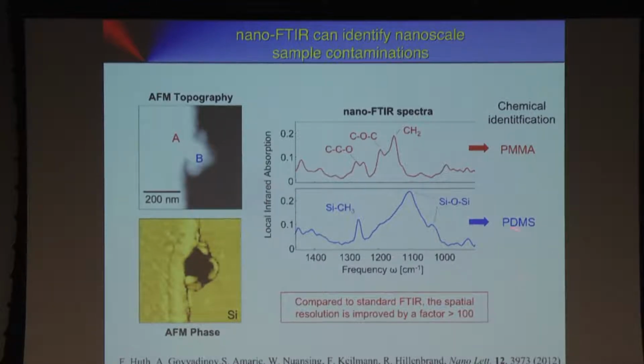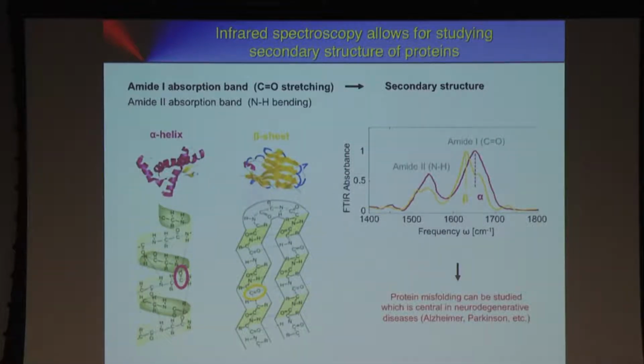It's kind of silicon. And it happened that the sample was simply contaminated, and we really didn't know it, and afterwards found out that it's absolutely normal that there's PDMS on this sample. Yeah, point out again, the resolution that we achieve here is in the range of 100 times better than with a standard FTIR microscope. Okay, so I want to stay with this technique, but switch the application. Now I'm going to biology, to protein spectroscopy.